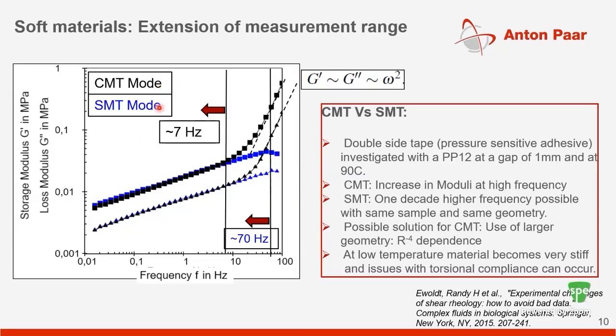Now, the advantage of having a multi-drive is you can actually investigate the same sample in SMT mode. When you have a separate motor transducer type device, you can see that you don't really see this spurious increase which happens in the CMT mode, and you can extend the characterization by almost a decade in frequency.